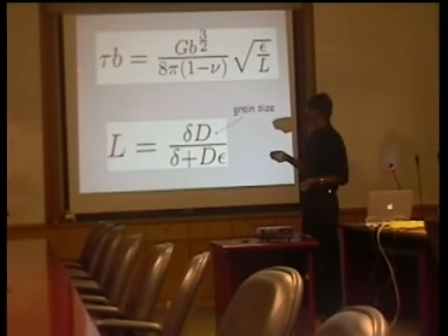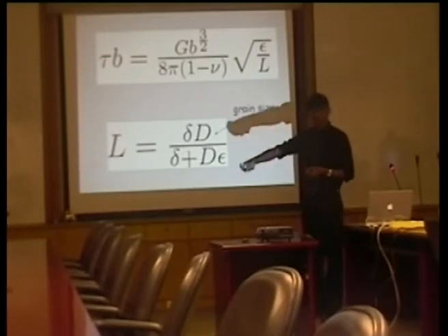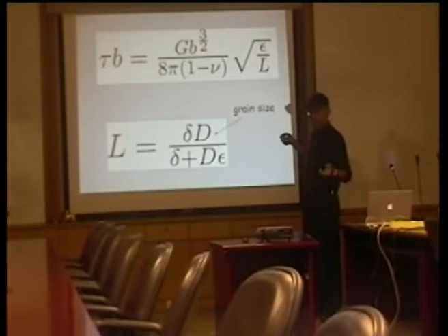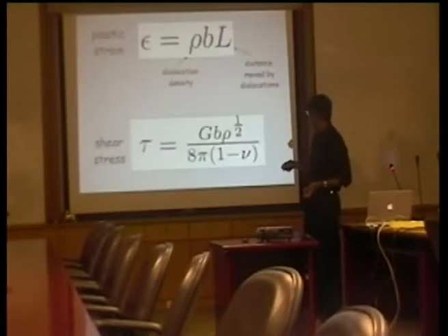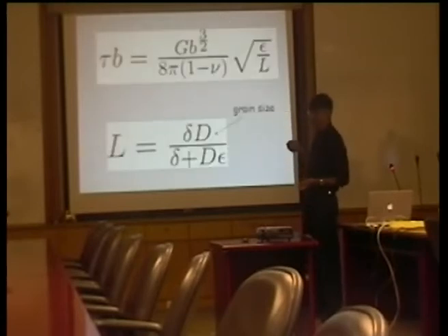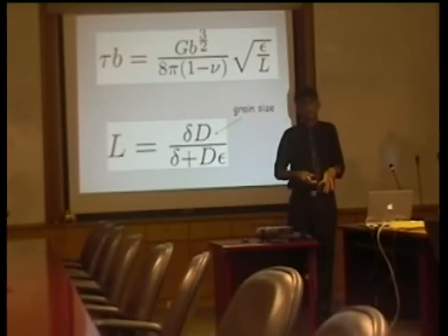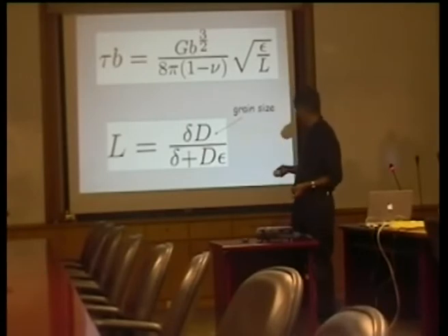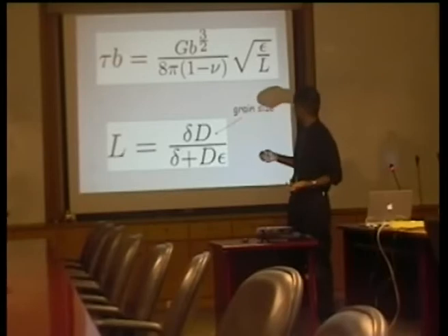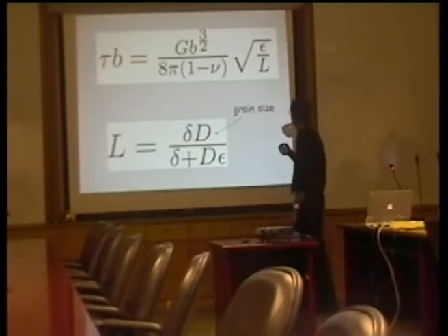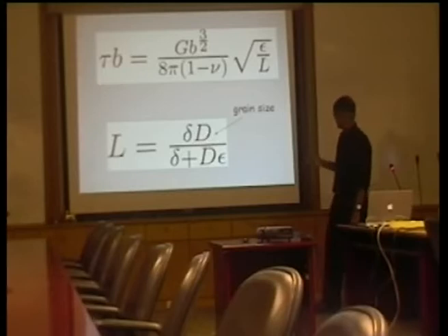I can combine those two equations and get this one, which relates the stress to the mean free distance of a dislocation. So there's nothing new here. These are just the two equations combined together, because if you look, they have the common factor rho. So if I just rearrange this, then I get the shear stress as a function of the mean free distance and epsilon. And this mean free distance depends on the grain size that we have, which is given by this capital D. So this is simply from the literature. We now have an equation for the shear stress, that means the stress required to move the dislocations, as a function of the grain size through L and of the plastic strain.